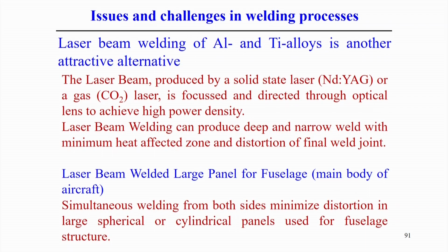Now, among other welding processes, laser beam welding of aluminum and titanium alloy is another alternative method. We know different types of solid state lasers and gas lasers are available, and the laser beam can produce a very narrow weld with minimum heat affected zone, high depth of penetration and small distortion as compared to other arc welding processes. So, in that sense, it addresses the difficulty of welding aluminum or titanium by conventional arc welding processes, and the laser beam welding process can be used.